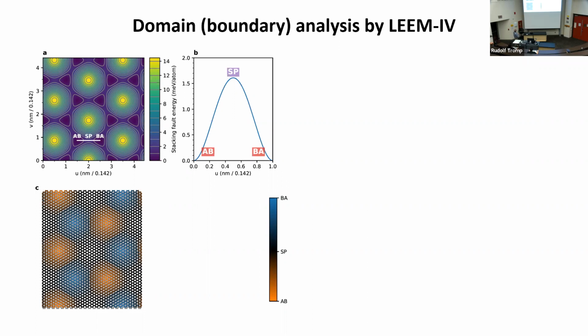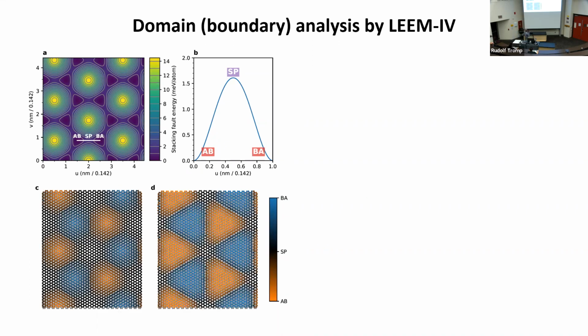And if you look at the energy, it turns out that this region where the two lattices are exactly on top of one another, theory tells you that is energetically very costly, right? So it doesn't really want to do that. And what happens instead is that these blue and these red regions push out and they minimize this area in the middle where they sit exactly on top of one another. And then there are saddle points between them, where it's like a partial dislocation. You go from one stacking to another stacking, right?